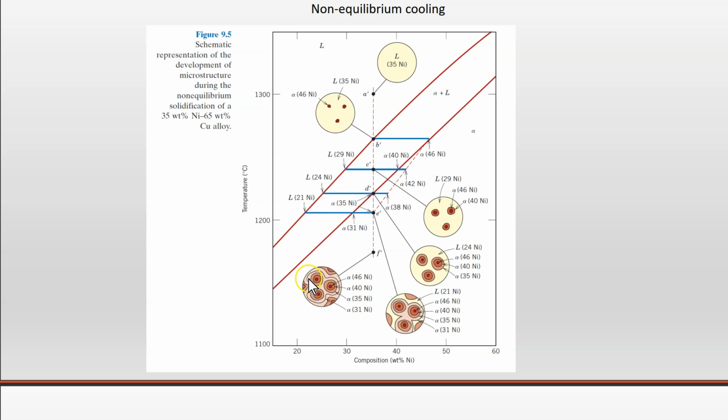And it's going to be prevented by homogenizing the material by holding it at a temperature below the solidus. Okay, so we don't want to introduce any liquid when we heat treat it. We just want to improve diffusion by increasing the temperature and allow it to homogenize.